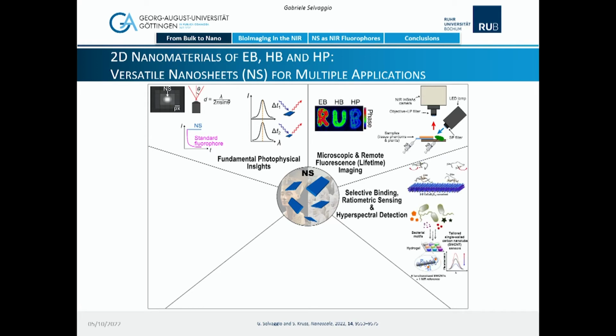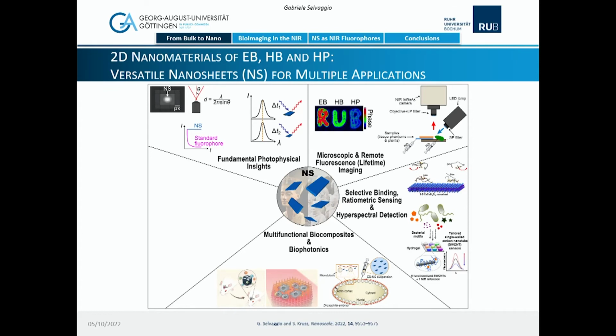There were then other works done by other research groups which show that, for example, you can exploit the typical high aspect ratio of Egyptian blue nanosheets, so this typical 2D geometry, to perform selective binding, more specifically selective enrichment of multiphosphopeptides, which is of high interest for mass spectrometry. Other works, on the other side, exploited the really stable fluorescence of Egyptian blue nanosheets as a reference signal for ratiometric sensing of bacteria within the frame of smart implants, for example, so a clear biotech application. Other works instead have focused on biophotonics applications, which I will describe more in detail in the next slides.